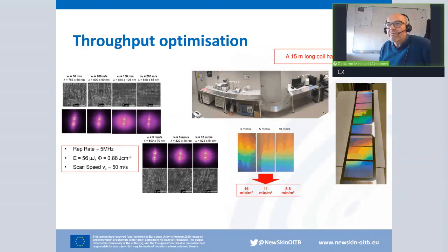Then we fixed the scan speed to 50 meters per second, and we tried to optimize the throughput by increasing the line speed of the coil of material, from 3 millimeters per second up to 10 millimeters per second. We found that it's still good at 10 millimeters per second, which corresponds to 5.5 minutes per square meter. Here you see some of the samples. We have textured a coil of stainless steel, 15 meters long, in nearly 1 hour.